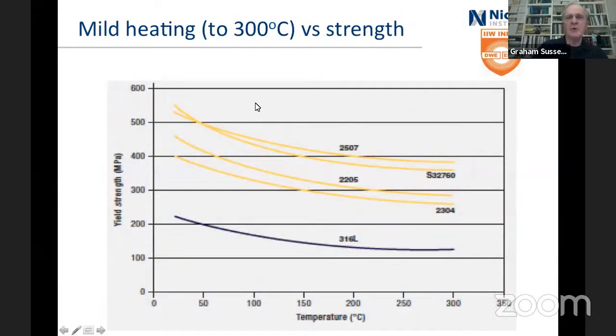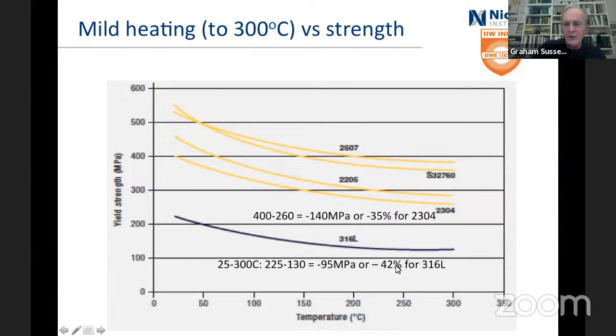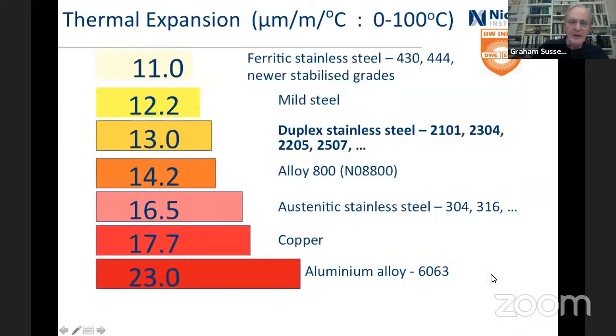Looking at mild heating, and I'm talking about 300 degrees, it's the thing that you're supposed not to do with duplexes because heating up above that temperature gets you up into a potential problem of embrittlement, but at 300 degrees, you should be reasonably safe. So look at 300 degrees from 25, 316, and you get about a 42% drop off. For 2304, same range, about 35%. And for the super duplex, you get again about 35%. So it is worth heating up a bit, but don't go beyond 300. And in fact, if you're talking about TUV, then don't go beyond about 270 because there is a potential problem once you get up to 475. I'll come back to that.